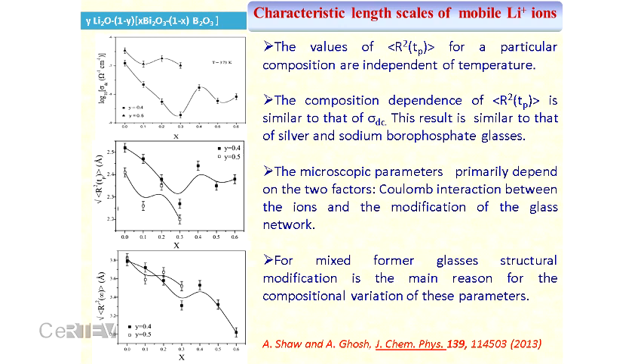Here I have shown some interesting results for some unconventional glass. Here you can see that boron oxide has been replaced by a heavy metal glass former. Bismuth oxide is a heavy metal glass former. You can see several minima, but in all cases the conductivity decreases. So it is called the negative glass former effect for bismuth glass. And we have also correlated it with the length scale, the value at the crossover point, and the long time behavior of the length scale. We can see these three parameters behave similarly: the DC conductivity, the crossover point, and the long time behavior. So this result is very surprising.